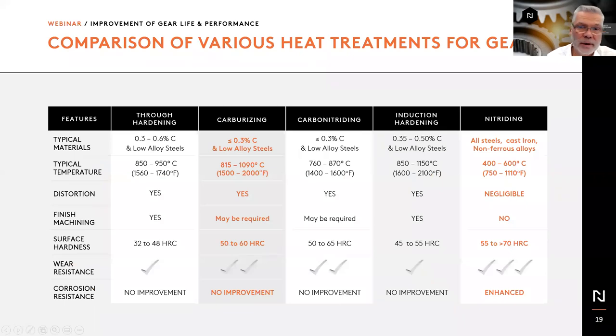So comparing the processes in a different way, you have types of materials. We went over this, and you see that typically, because carburizing relies on the diffusion of carbon, you'll see usually steels that have less than 0.3% of carbon, and they may be extremely low carbon steels as well. Whereas in nitriding, everything is possible. However, here we say all steels, cast iron, non-ferrous alloys, while most high-quality gears are made from steels that are formulated for nitriding. What really is the huge difference?